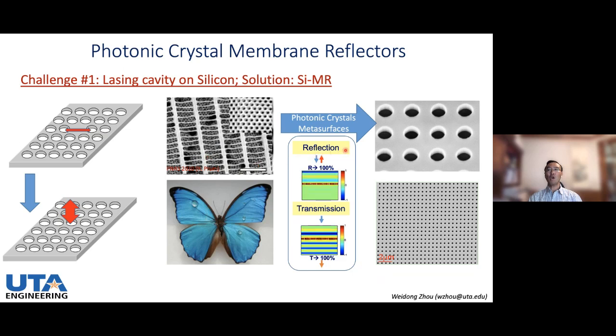And that's what we have been working on for many years now: drilling holes in thin-film silicon. You can see we use the E-beam, electron beam lithography process for nanofabrication. The hole size is about 100 to 500 nanometers with a periodicity of about 1 micron. And we can make it, of course, over a large area. If you design it right, indeed, you can get 100% reflection or 100% transmission, depending on the wavelength. So you can design that.